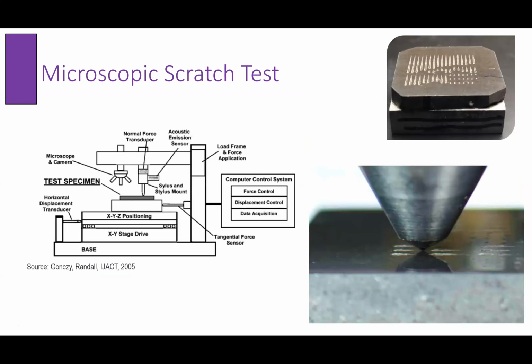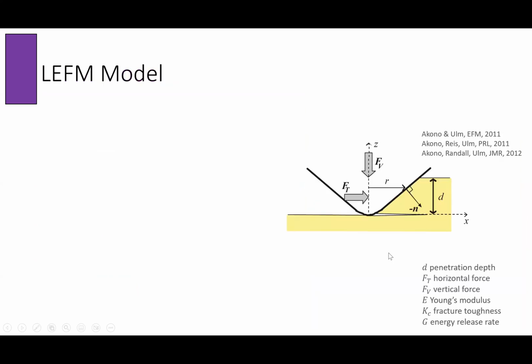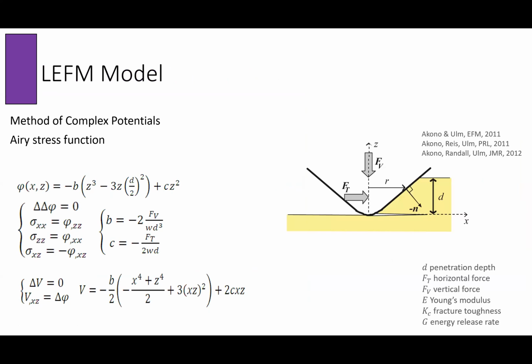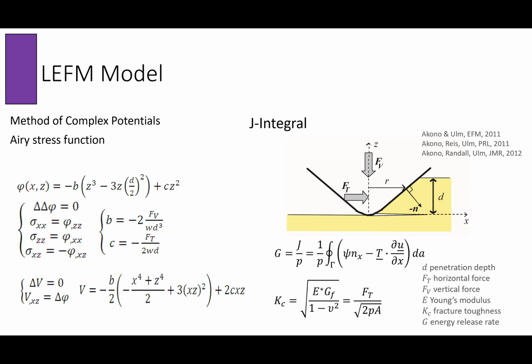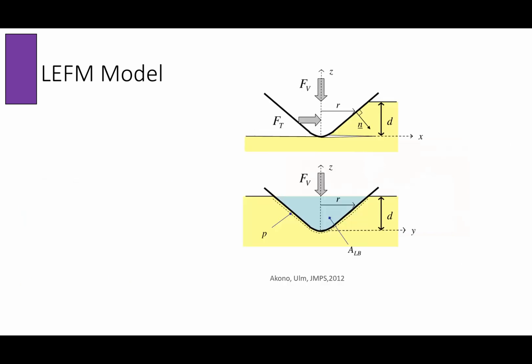So these are some more images. This is a schematic of the experimental setup that we have. And this is a digital photography image of the probe after scratch test in this case. So I'm going to go very quickly on the LEFM model that I developed as part of my PhD thesis. But the idea basically is to evaluate the stress field around the probe using the method of complex potentials. And then after that, we apply the J integral to be able to relate the fracture toughness to the force and the penetration depth.